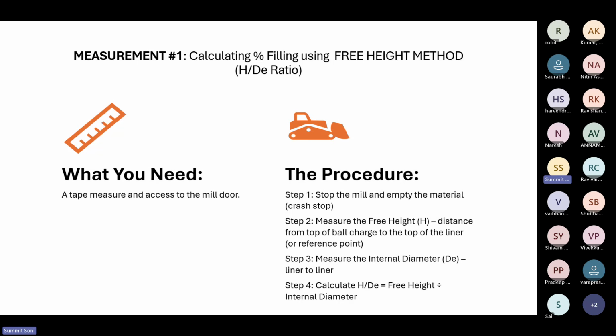That's the distance from the top of the ball charge to the top of the liner or your reference point. It's usually the top of the liner. The middle part of the liner where the wave is in the middle. So you don't measure at the highest point of the wave. You don't measure at the lowest point of the wave, somewhere in between, if that allows. Let's say if your perpendicular direction hits the top of the wave, then you make sure that you measure all across the length of the mill on the top of the wave, on the liner. This is the most basic confusion people usually have.